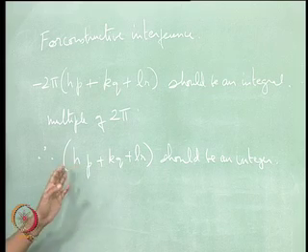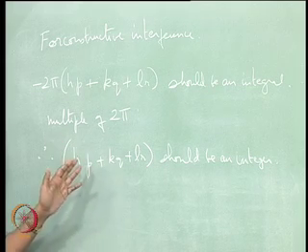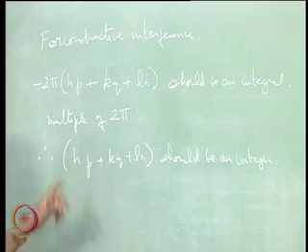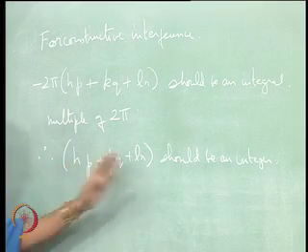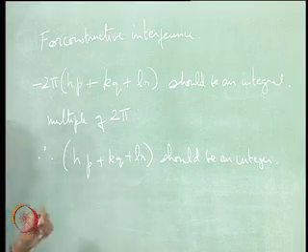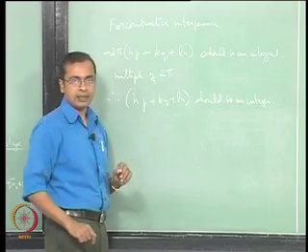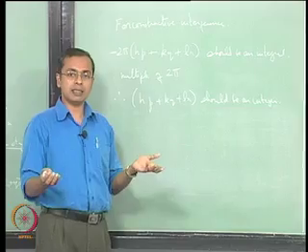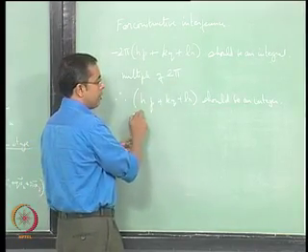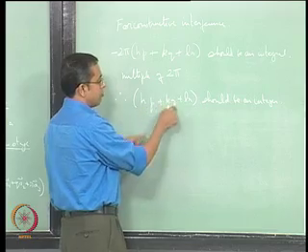However, we are forced to deal with the situation wherein for constructive interference to occur, a sum of these terms hp plus kq plus lr should be an integer. In this, p, q and r are already integers, and they could be any integer. So for this complete sum to be an integer regardless of the values of p, q and r,